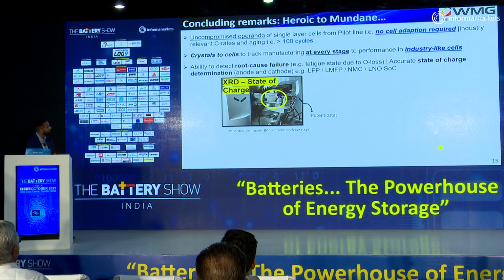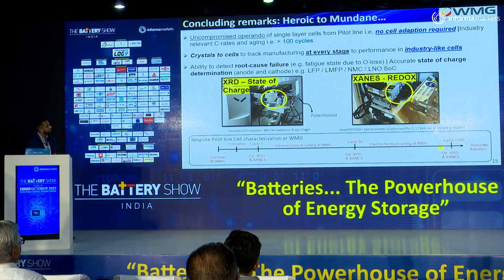Well, here is an image of our diffractometer, a Malvern Panalytical Empyrean, and we use a molybdenum X-ray source to pass through the pouch cell, and this pouch cell is connected to a potentiostat, and we use the BioLogic potentiostat systems. Now, the X-ray absorption spectroscopy tracks chemical changes in our cell to look at charge compensation. This is our XANES measurements. And what we have is at every stage, we have our cell build, formation, our cycle, and we have control over every single stage in our material.